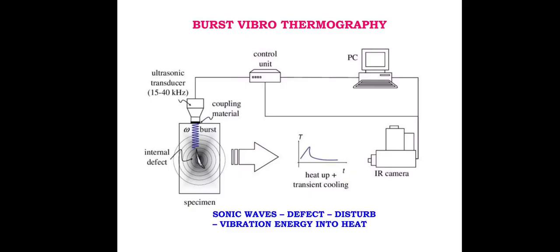Introduction of the couplant material like a piece of fabric, water-based gel, or aluminum between the transducer and the specimen will reduce loss. A bad couplant implies poor ultrasonic sound transmission, but more seriously, it creates unwanted heat in the vicinity of the ultrasonic injection point. After the mechanical sound waves or ultrasonics are injected into the specimen, they travel through the material and dissipate their energy mostly at the defects so heat is locally released. The thermal waves then travel by conduction to the surface where they can be detected with an IR camera. Then the data is processed and displayed in the computer and defects are identified.